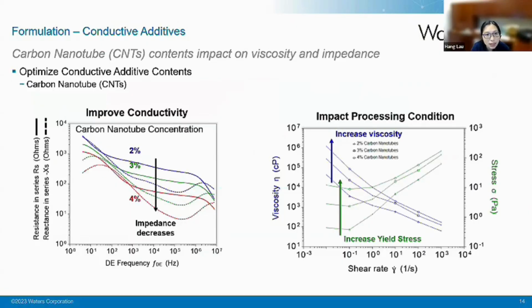So for the conductive network, people have been using carbon black. Some people and other new innovations are trying carbon nanotubes to increase the conductivity or reduce the material. So we know that increasing the conductive additive will reduce the resistance, so you will have a better conductivity. But oftentimes when you increase those, you will actually increase your viscosity and increase yield stress.